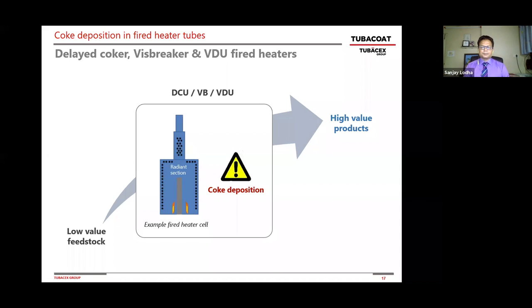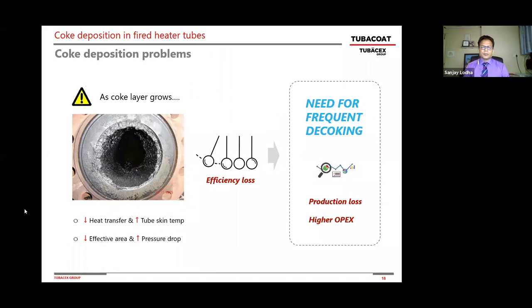Next slide, please. As you can see looking through the tube, as the coke layer grows, of course, your heat transfer reduces, you have tube skin temperature that goes up, you have hot spots, your effective heat transfer area is reduced, you have a pressure drop, and you come to the point of end of run, either due to high temperatures or due to pressure drop. What you have to do is shut down, or do online spalling, or steam air decoking, or mechanical pigging. Next slide, please.